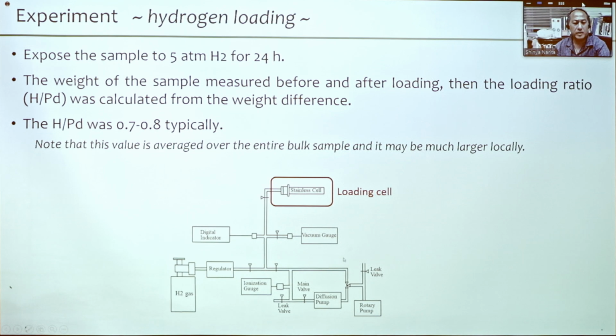So this is a setup of the hydrogen loading system. This is a loading cell. Then we put the sample here. Then after evacuation of the system, the hydrogen was introduced in the cell with the pressure of 5 atm. Then the sample was exposed for 24 hours. Then the weight of the sample was measured before and after loading, then the loading ratio, or so-called H over palladium, was calculated from the weight difference. The typical loading ratio was 0.7 to 0.8. And here I should note that this loading ratio value is averaged over the entire sample, and it may be much larger locally.